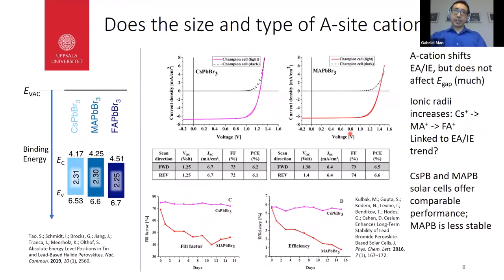Others have looked at it with a variety of techniques. So for example, Selena's group has used direct and inverse photoemission to examine the electron affinity, which is the conduction band edge to vacuum level energy offset, and the ionization energy, which is the valence band edge to vacuum level offset. And so what they found is that the type of A-site cation doesn't really change the magnitude of the band gap very much, however, there seems to be a trend in the electron affinity and ionization energy. So these parameters are quite important for device interfaces, for example. So when you want to combine a carrier-selective contact with the absorber.